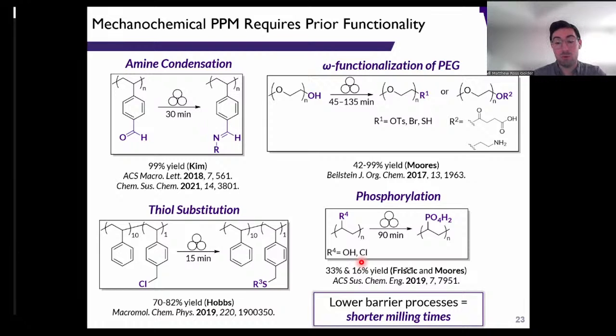Right, we're milling on the order of tens of minutes here, and that's because these are all really low barrier processes. Because of that, we don't have to think as hard about competing chain scission reactions. Right, that was the whole point of the liquid assisted grinding in our polymer synthesis towards the beginning of this talk. I mentioned at the very beginning that there's this whole idea from Staudinger and others that exogenous mechanical force can break down polymer chains into these macroscopic radicals.